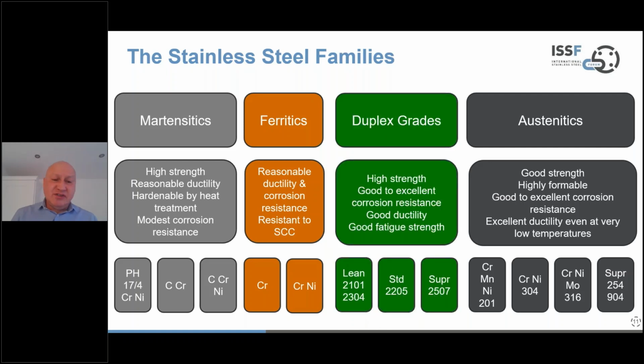Now, sitting between them is the new kid on the block, the duplex grades. The new kid on the block, they're what, 90 years old or something of that order. But these combine the best of both worlds, the best of the austenitics, the best of the ferritics. Really high strength, good to excellent corrosion resistance, pretty good ductility, and good fatigue strength. And these are typically the lean duplex with 21% chromium, a little over 1% nickel, or the 22% chromium, almost 5% nickel, molybdenum steels. I'm getting my terms mixed up, so please excuse me for that.